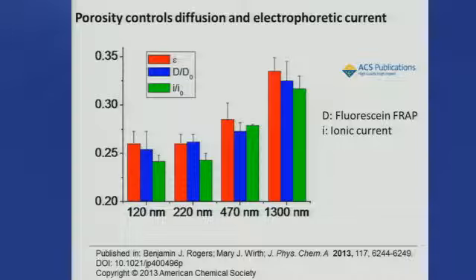And it was interesting to us because in the chromatographic literature, they would tell you, no, there's a factor of roughly 2 here, and in the chemical engineering literature. But in the polymer literature, this is what they use. And so we wondered, what are you actually supposed to use when you talk about obstructed diffusion? And the obstructed diffusion looks to us like it's just simply related to this fractional free volume.